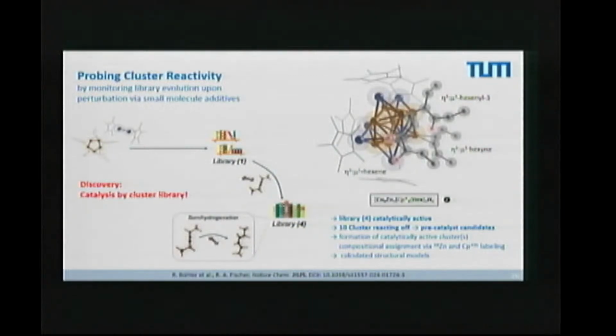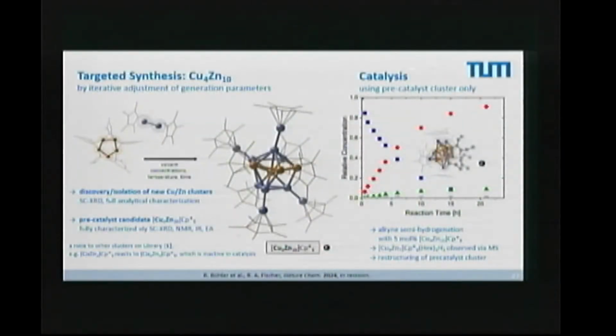So once we saw this kind of catalysis going on with the whole library, and we found a new species formed, we were looking at those species in the library which disappear. So there are species which stay, for example, the triangle. The triangle is a dead thing. It just sits there and it's lazy. Others as well. And some disappear. I don't know what my student did to choose one of the disappearing to hunt for. So he was choosing this one, the copper 4 zinc 10 cluster, which we have not been paying attention before.